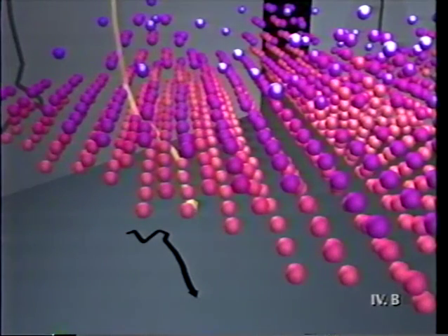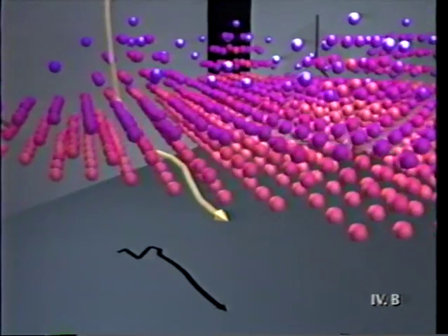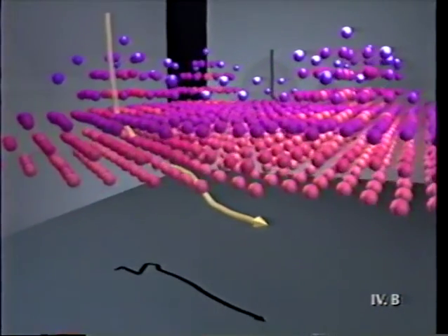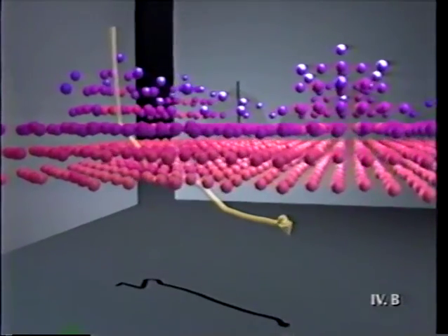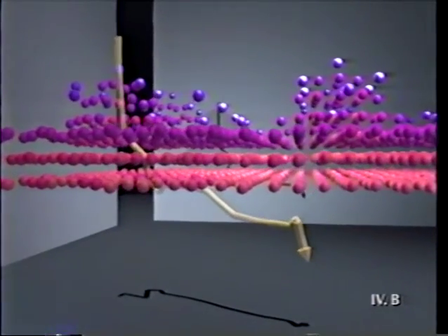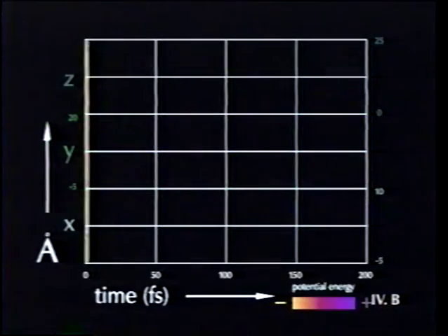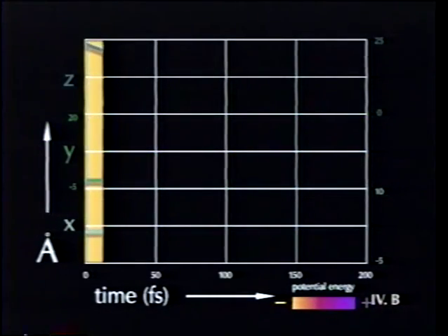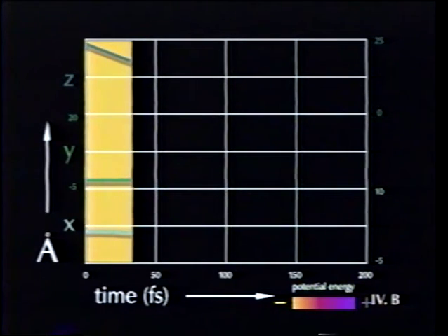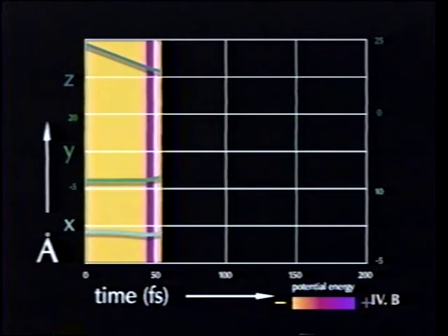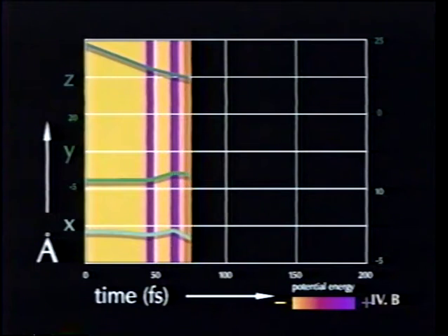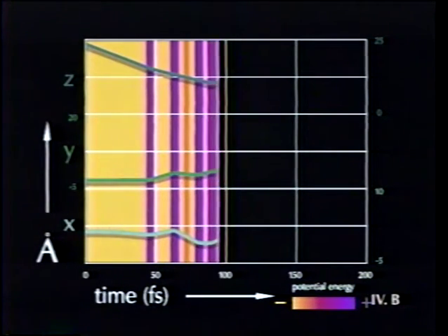Remember that there are lattice atoms present beneath the ones that were visualized. Their interactions are included in the molecular dynamics code. 2 more hard collisions occur in rapid succession, which drive the particle deep into the lattice. The entire plot of the hydrogen atom's position versus time shows binary collisions occurring on average every 5.8 angstroms.